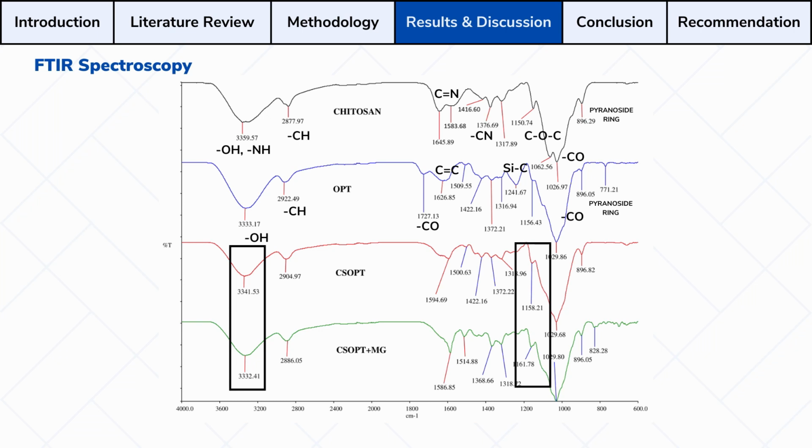The bands corresponding to hydroxyl and amino experience a slight shift to lower frequencies, indicating a disruption in the hydrogen bonding network of chitosan between acetic acid, imidazolium ionic liquid, and chitosan chain. This shift was attributed to the reconfiguration of a new hydrogen bonding network of chitosan. After the adsorption of Malachite green, a new peak appeared at wave number 1500, which indicates that there was an increase of nitrogen in the compound. Additionally, the intensity of hydroxyl and amino peaks increased slightly, corresponding to the increased amount of nitrogen in the compound.